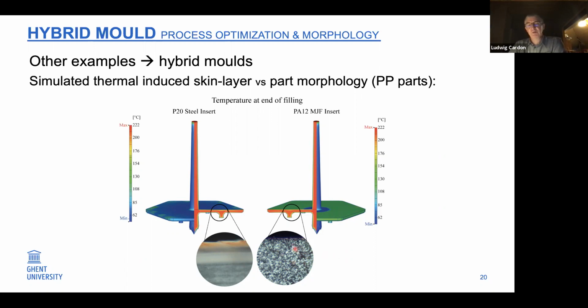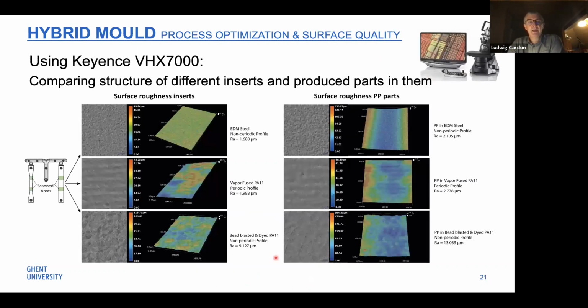Well, this is very important because the difference in crystallinity and morphology will finally result in a difference in, for instance, impact behavior and brittleness of your material. So also what we investigate in that case is, let's say, the surface structure. I briefly showed that here as an example. We do process optimization to define what's the minimum needed holding pressure.